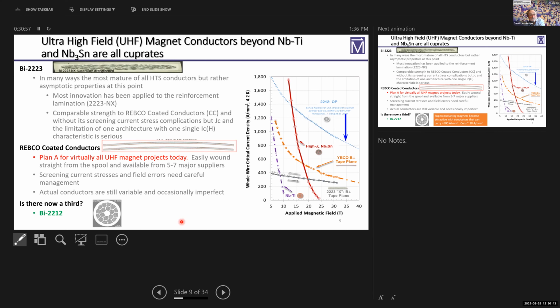And a big advantage of this is that although the material itself is anisotropic at the grain level, because we have all orientations here, it's macroscopically isotropic. And there are real problems in making magnets associated with dealing with the anisotropy here, because this method of manufacture here is almost a single crystal by the mile. So it's an actual triumph of materials engineering, but there are some nightmarish aspects of what happens when you have it.